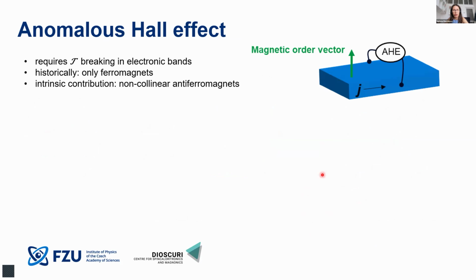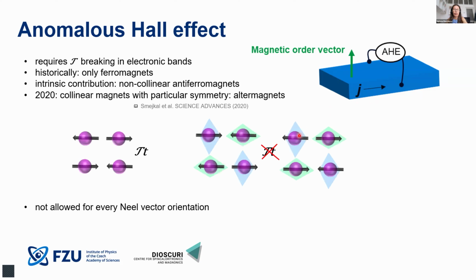let me just very briefly say what the anomalous Hall effect refers to, and why we think it's a good tool to test the presence of altermagnetism. I already said that it's an effect which generates a transversal voltage perpendicular to the magnetic order vector and the current. It was previously thought to exist only in ferromagnets. Lately, in the last 20 years, we also know that it exists in non-collinear antiferromagnets. However, in the collinear ones, it's simply forbidden by symmetry, right? Because this is an effect which relies on time reversal symmetry breaking in the electronic bands. And if we consider the conventional antiferromagnet, some sort of square lattice, then this is a prime example of a PT symmetric material.